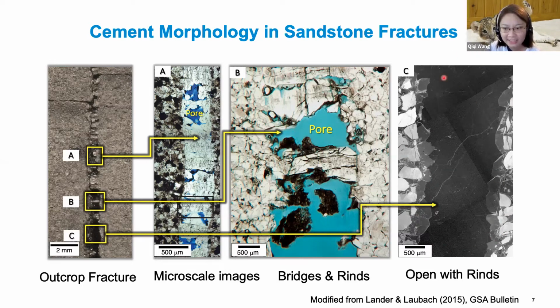That would be the case C. And in the intermediate position, the case B, we see a lot of pore space within the fracture, and we commonly see what we call bridge structures, where a pillar of quartz cement bridges across the natural fracture, spans from one wall to the other. And these cement bridges contain valuable information about fracture timing, and they can reveal the history of diagenesis and deformation of the rock. It's really pretty cool, and we will get into that later.